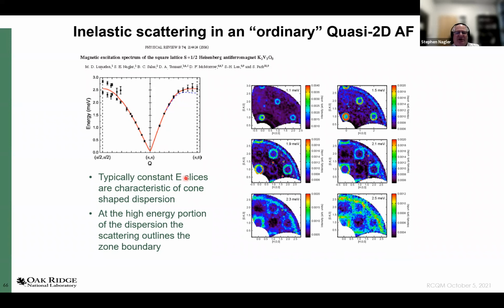That happens to be a square lattice, but if I look over here at slices of constant energy now over the 2-dimensional surface, I'll see around each one of these antiferromagnetic points a circle with a radius that increases as the energy increases. These are just cones of dispersion. And eventually, when I'm close to the zone boundary, I sort of see the outline of the zone boundary. That's what spin waves sort of look like conventionally if I do a constant E plane, which is what we do a lot of times with the time of flight inelastic data.